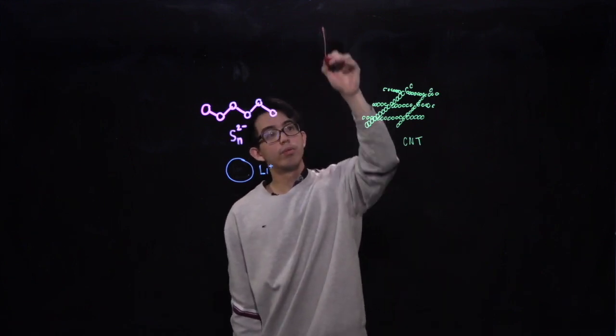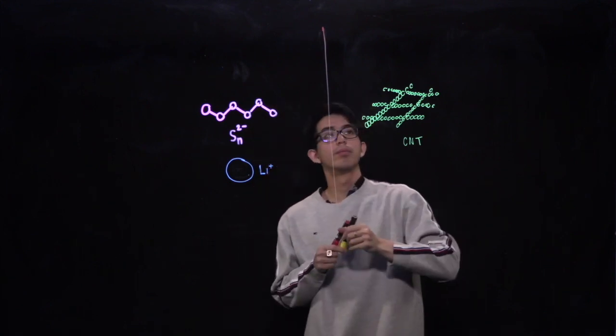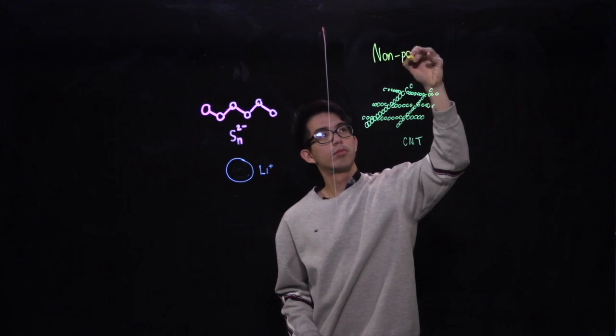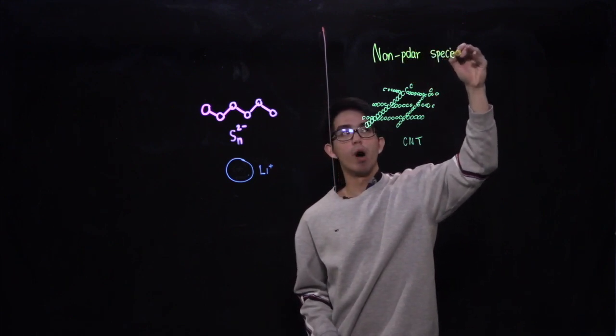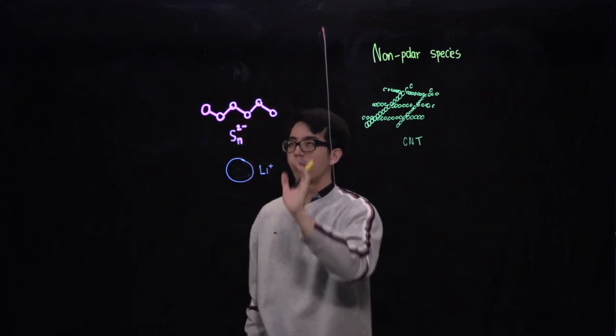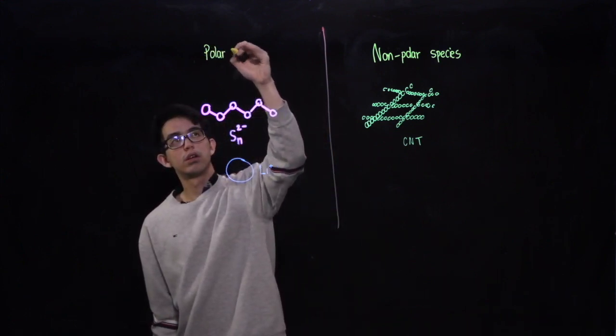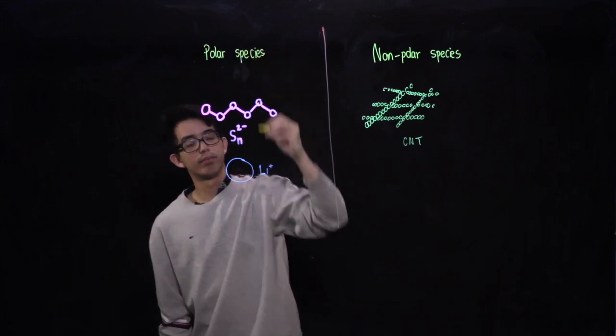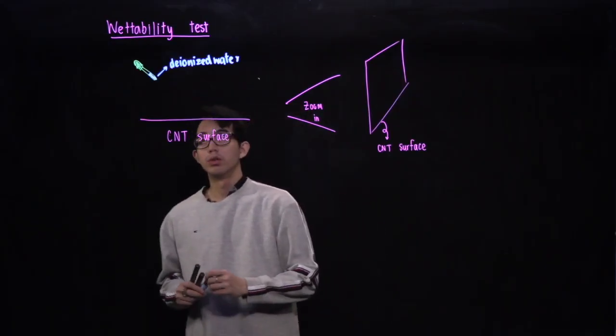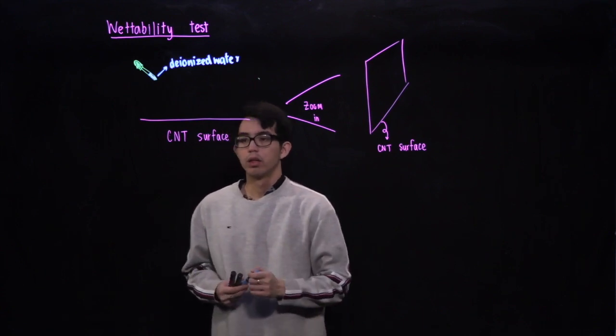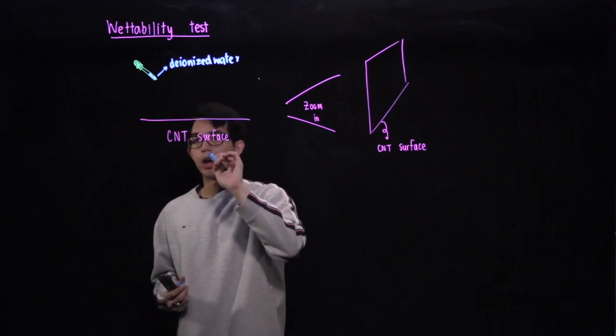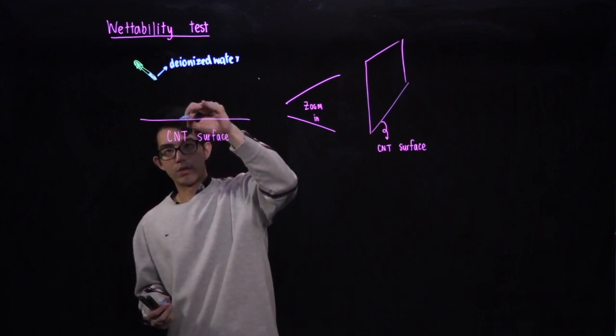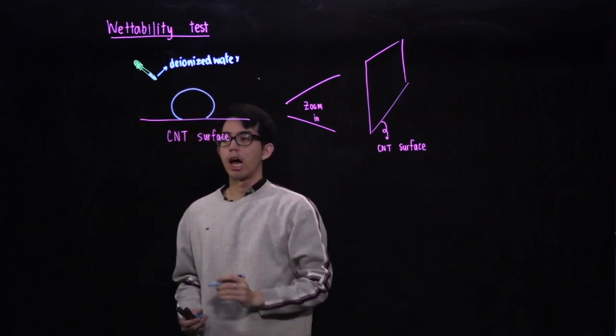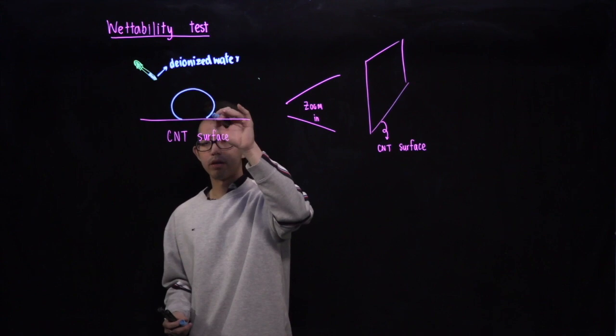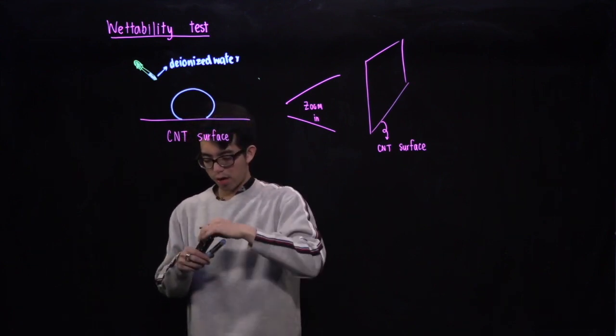This carbon nanoparticle is a non-polar species, while our species of interest are all polar species. Therefore, when we do the wettability test on the carbon nanoparticle surface by dropping deionized water onto the surface, the droplet of deionized water will form a pretty large contact angle between the droplet and the surface. In this case, it's 112.8.